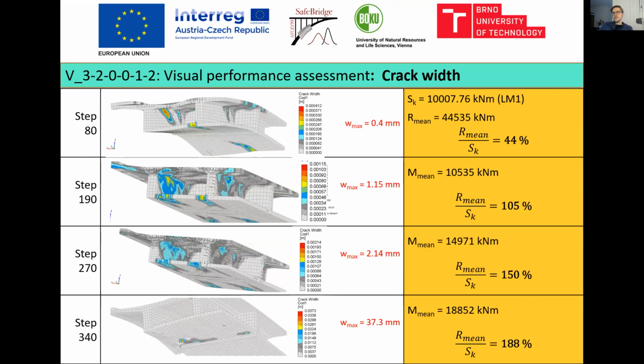So our goal was to find a model that predicts the behavior best, and we made a visual performance assessment of the different models. First the crack width. Here's model 3.2, and we analyzed it at 4 different load steps. First at step 80, that's about 40 to 50% of the corresponding characteristic load. The crack width was about, in this case, 0.4 millimeters, and we compared it to the other models. At around 100% of the characteristic load, the crack width is 1.1 millimeters.